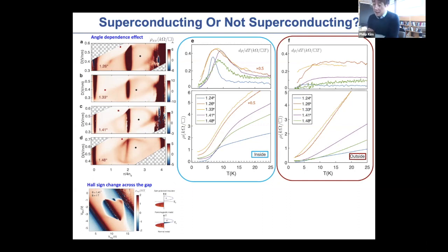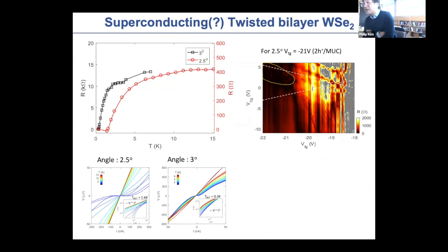But in some of the other samples, like the twisted tungsten diselenide, you also see a very low resistance state show up. But it's under very particular conditions and a few gate choices, so it's not clear whether a zero resistance state alone is enough to claim superconductivity, and one should be able to see other possibilities in this type of sample. So the problem that experimentalists face is: is there a way to create homogeneous samples in a reliable way, or is there another type of measurement other than transport, preferentially some thermodynamic type of measurement, to follow this superconductivity as well as the correlated insulator?